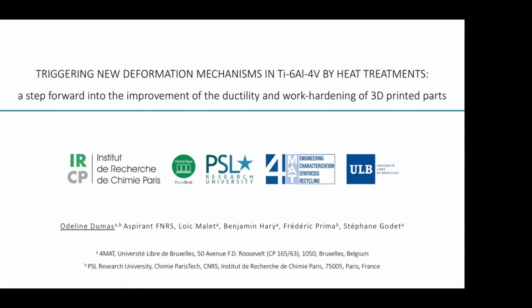I don't think on that part, because we looked at the martensite of the deformation on 3D printing, and we could also find some orientation. But you have some differences because the size of the martensite is not exactly the same. The morphology of the dual phase microstructure in general changes a bit. And you also don't have the same texture, and we saw that the texture has an influence on this reorientation. But it's more about that than the constraint.